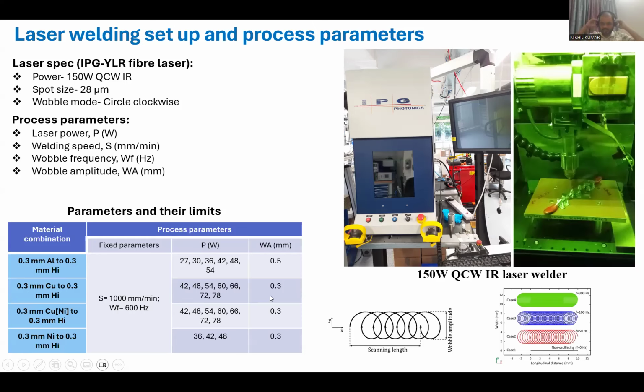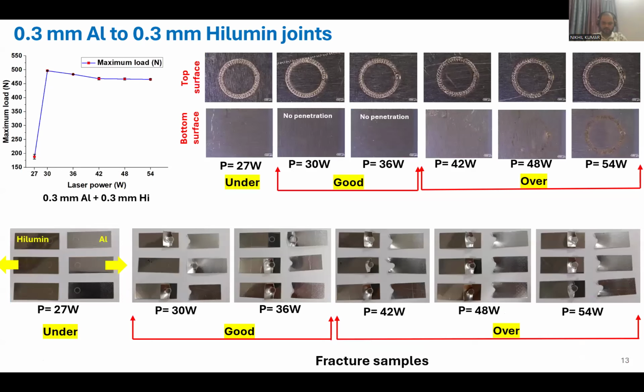Yeah, so this is one of the examples. I'm showing the aluminum to Hilumin weld joint. As I mentioned, I have measured the weld strength, lap shear strength. What I have seen here in the top picture is the top view of the weld seam, and this is the bottom face of the bottom sheet. So this is the bottom face of the bottom sheet, and this is the top surface of the top sheet. This way, you can identify which surface is 100% penetrated. From left to right, you can see this one is 100% penetrated, the bottom sheet.